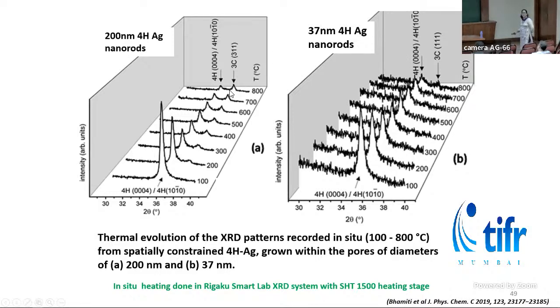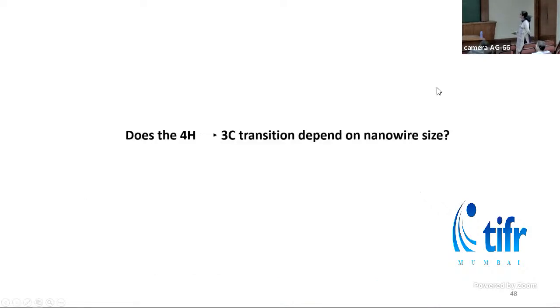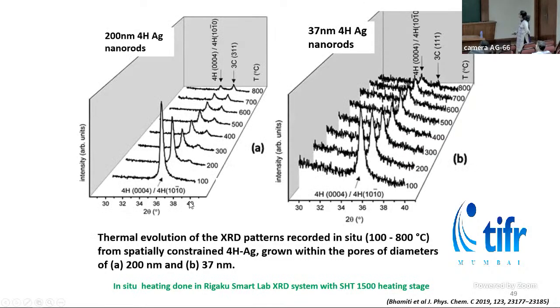Same experiment when we did with 37 nanometer 4H silver wires. This is the XRD data of the sample. Here we can see that at 200 degrees centigrade, there is no 3C phase, and at 800 degrees centigrade also, we can see only a little amount of 3C phase present in the sample.